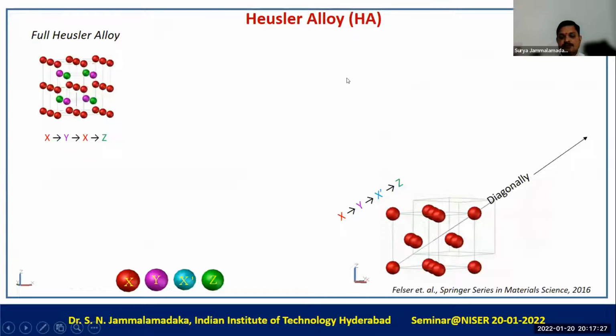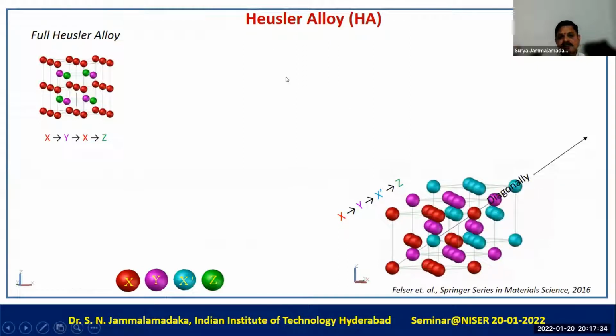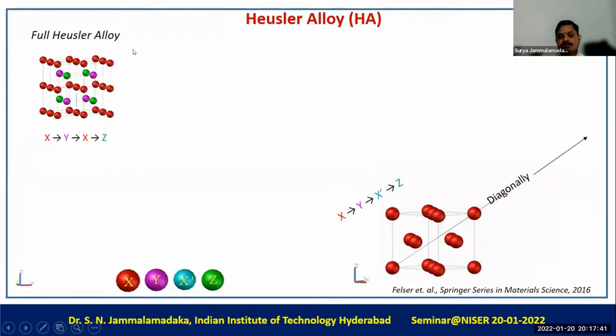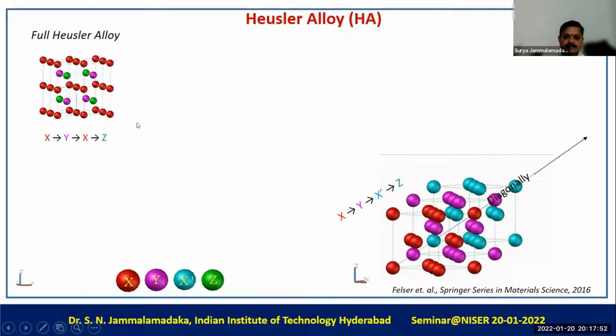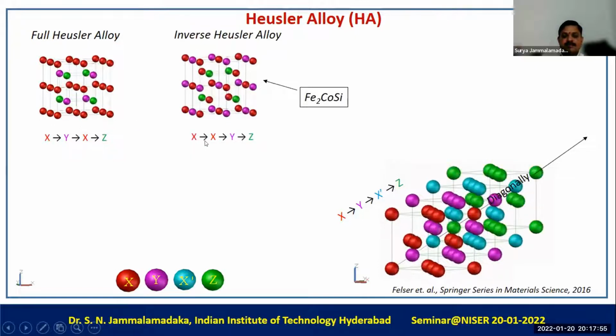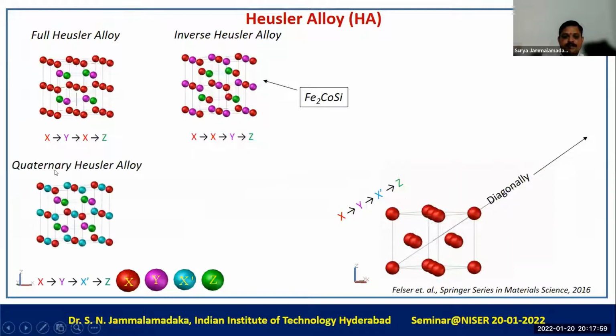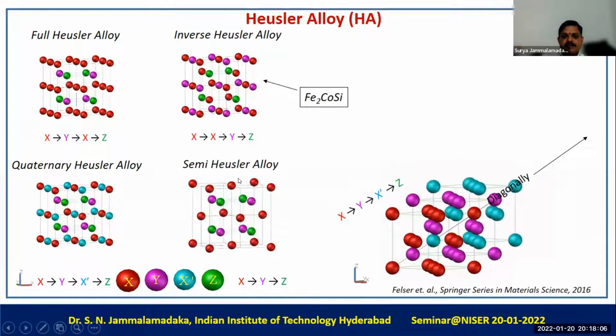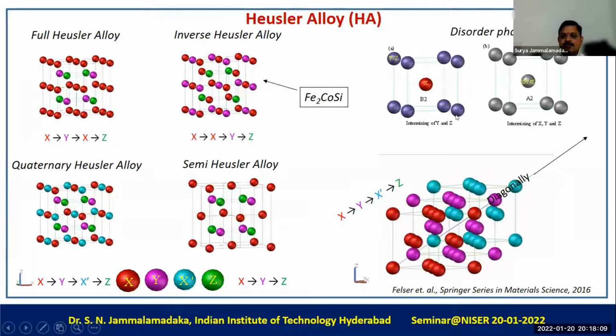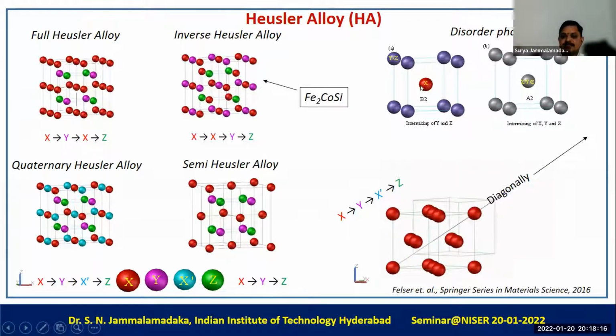Now, if you look at the Heusler alloys, as I mentioned, they have very high spin polarization. We must understand the structure of these Heusler alloy compounds. They form in four varieties of structures. One is the full Heusler alloy, where along the diagonal the atomic arrangement will be X, Y, X, Z. In the inverse Heusler alloy, the atomic arrangement along the diagonal will be X, X, Y, Z. In the quaternary Heusler alloys, along the diagonal, the atomic arrangement will be X, Y, X prime, Z. And in the semi-Heusler alloy, it will be X, Y, and Z. There also exist disordered phases. Suppose the intermixing of Y and Z happens, that is called the B2 phase.